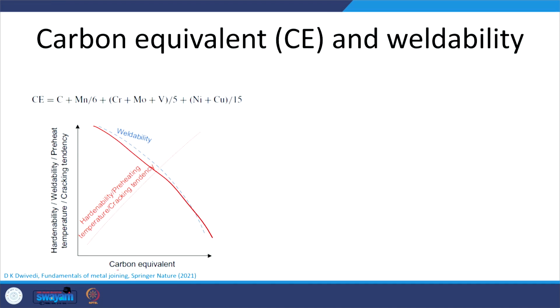So, the carbon equivalent is calculated for alloy steels using this equation, and we can see that hardenability, weldability, preheat temperature requirement and cracking tendency are all affected by the carbon equivalent. Weldability comes down with the increase of the carbon equivalent, and other parameters like hardenability, preheating requirement and cracking tendency also worsen with the increase of the carbon equivalent, because it will require greater precautions, greater steps and more sophisticated procedures for development of a sound weld joint.